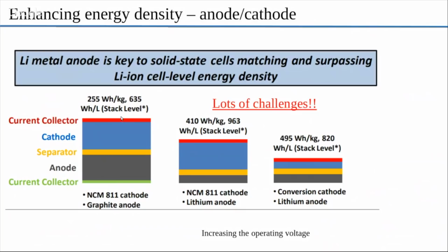Now, if you want to go even further, let's say you have a Tesla Semi coming up and you want a lot of range for the Semi, then people are working on how to do that. There are different approaches, but there are many, many challenges. One approach is you replace the graphite anode that we saw on the previous slide with a pure lithium anode. If you use pure lithium metal, there's a problem called dendrite formation. Dendrites are like sharp teeth. They grow out of these structures and poke through the cell and short circuit it, making the whole cell defunct. That's a big problem, and people are working on using lithium anodes. If they can succeed, we will see about 410 watt hour per kilogram.